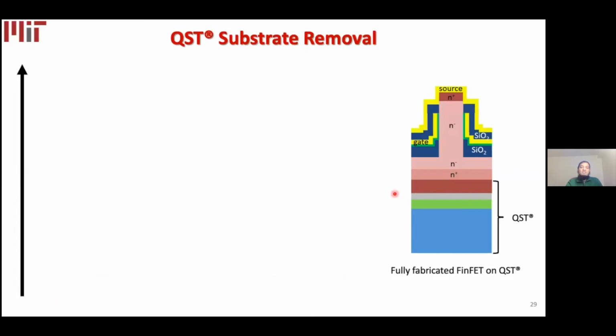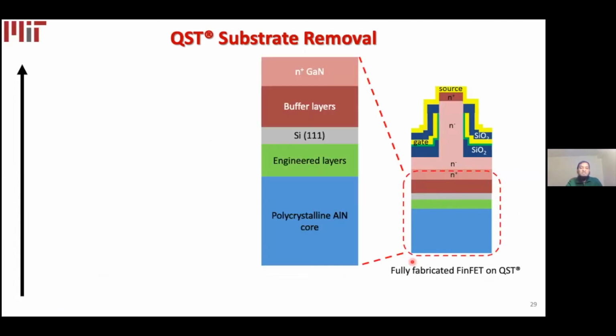Now, the substrate removal is very challenging because of the complicated structure of this engineered substrate itself. If you look closely at the substrate underneath the N+ gallium nitride drain, it has many layers, such as GaN buffer layers, silicon 111, the engineered layers, and the polycrystalline aluminum nitride core.